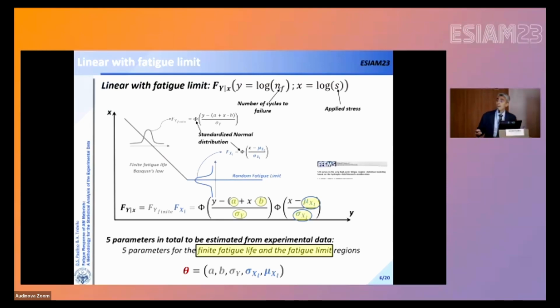And then how can we put together these two sources of variability? It can be demonstrated that the probability distribution function is just the product of the distribution of the finite fatigue life region times the distribution of the random fatigue limit, so that you will have a unified model that can describe the two regions.